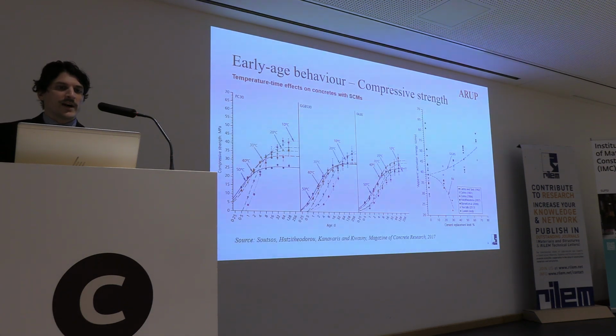And back then, we were quite interested in how temperature and time affect concrete with supplementary cementitious materials. Because in construction, supplementary cementitious materials were normally not very much included in high-speed or fast-track construction because of some strengthening issues, or because the understanding of how the strength develops was not well provided. So this was something that we were investigating, in this case in terms of slags and fly ashes, and we were evaluating the temperature sensitivities of the mixes.